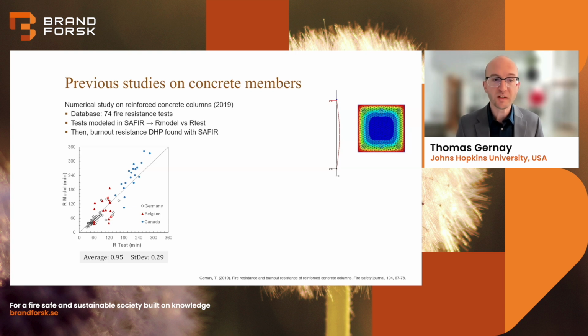The results are plotted on the screen. As you can see, the average agreement in terms of prediction versus test is fairly good at 0.95. However, there is still a very large dispersion, which indicates that it is not trivial to capture all uncertainties when modeling standard fire resistance tests on reinforced concrete members. And in some cases, obviously, there is uncertainty in the models.